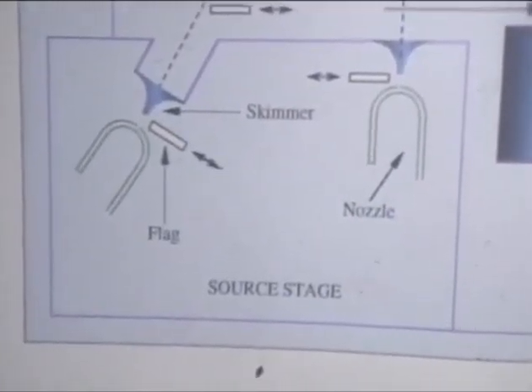And the technique here, for most of what I'm going to say, is supersonic molecular beams. So we follow catalytic reactions at a single crystal surface here, so that the surface is totally well defined, and it's followed by beaming two reactants at the surface using two molecular beam sources. So beam source 1, beam source 2, where we can state control the incoming molecules. So we can send them in, as you will see, this is critically important, with a well-defined translational, vibrational, and rotational energy. And we can then see what is critically important in the dissociation of the molecule.